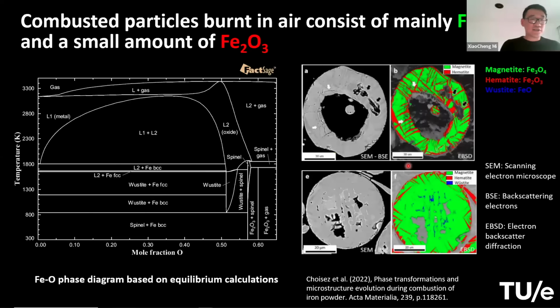For this we need to take a look at the thermodynamic equilibrium phase diagram. This phase diagram shows temperature on the y-axis, and on the x-axis the mole fraction of oxygen in the whole Fe and O system. So above this line here, this is the liquid phase. L1 is liquid iron, or relatively low oxygen-containing liquid. L2 is normally considered the liquid iron oxide. So under this dome, you have an immiscible mixture of L1 and L2.